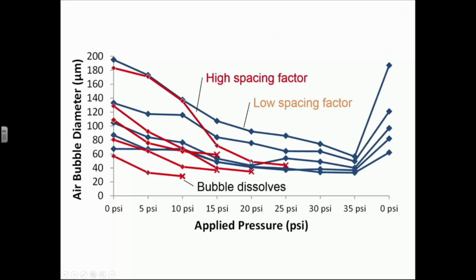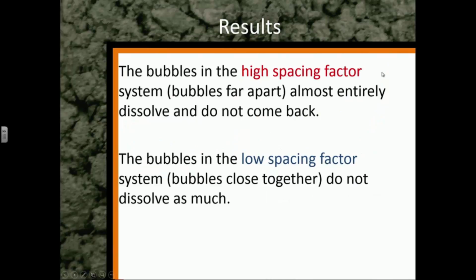At 20 psi, there's a major difference. But by 25 psi, this X means the bubble dissolved. But look at the blue one. It kept going, and guess what? When you decrease the pressure, the bubble comes back. And it's very similar in size, or close to being the same size as what it originally was. This means that bubbles in a high spacing factor system, bubbles far apart, almost entirely dissolve when you pressurize them. Not totally, but a lot of them dissolve and do not come back. But the bubbles in the low spacing factor system, bubbles close together, do not dissolve as much.